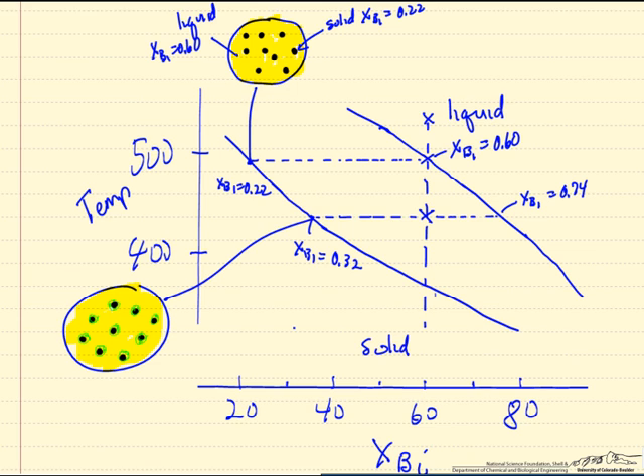I've schematically represented this where this is a cross section. This yellow now is the liquid with composition 0.74. These little green sections, since we have this core shell structure, have composition 0.32, but we still have the other solid inside with 0.22.